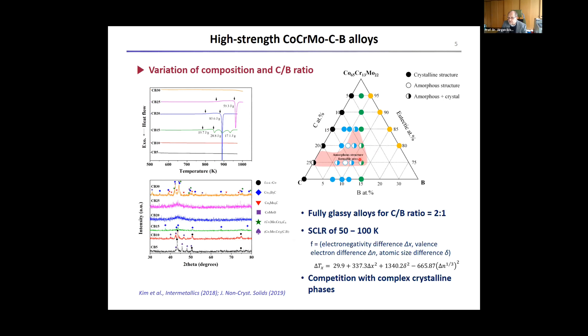The interesting feature of this glassy structure is that it has a relatively wide supercooled liquid region — basically the temperature region between the glass transition temperature and the crystallization temperature. If this region is something like 50 to 100 K, it gives you a temperature regime where you can easily shape such a glassy structure more or less like a polymer, making it quite attractive for shaping relatively complex parts.